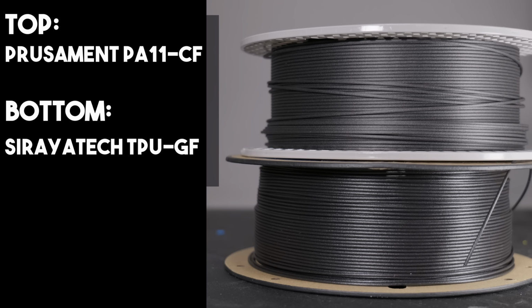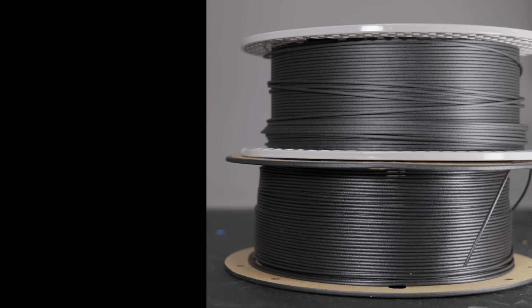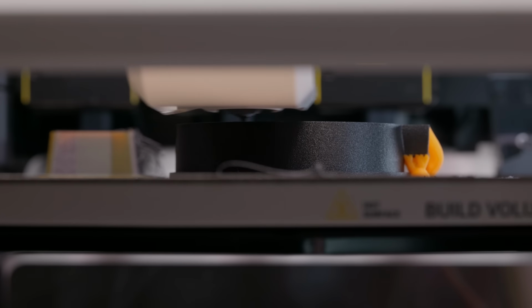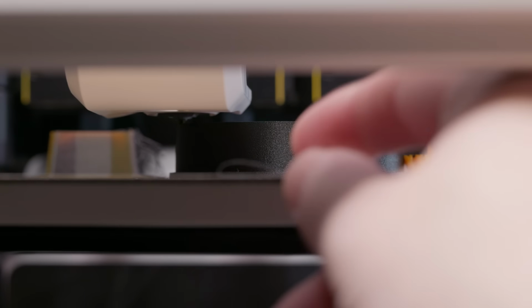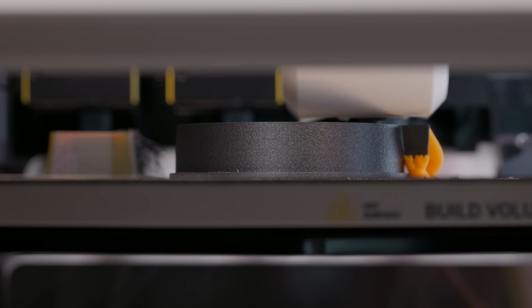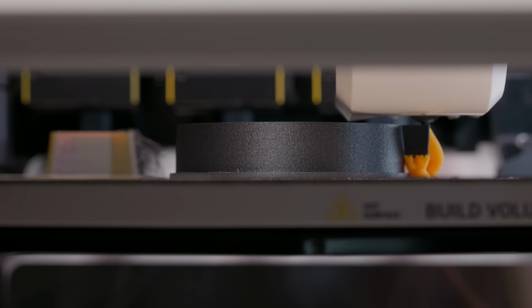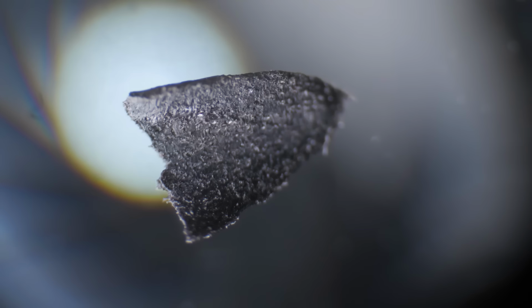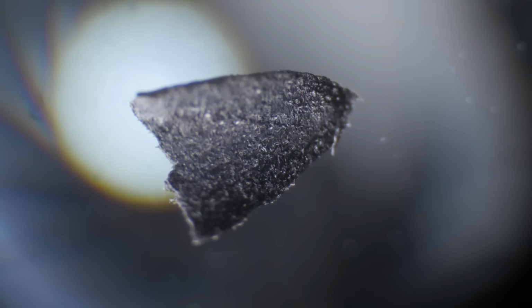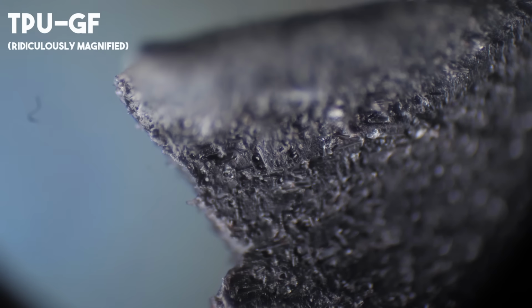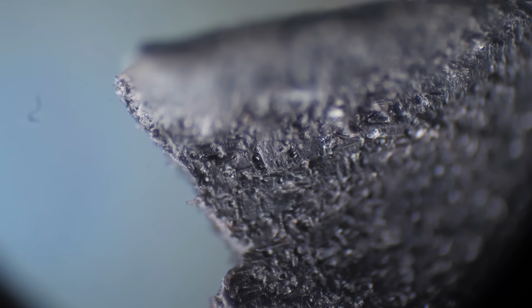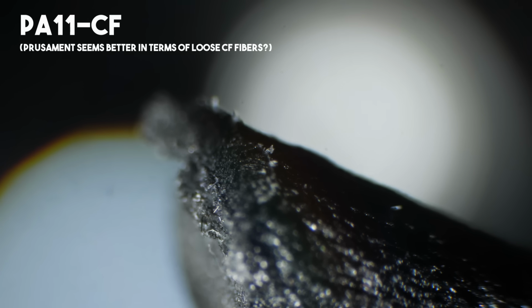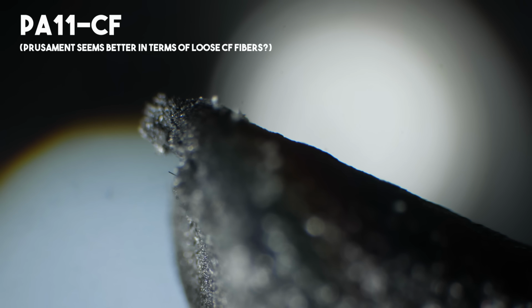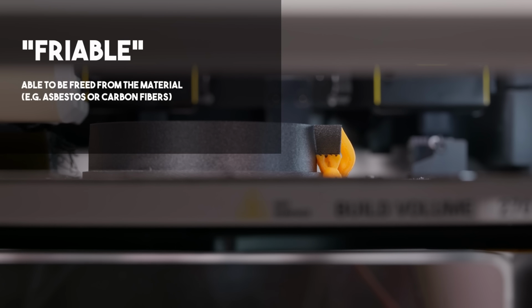The other interesting thing about GF filaments in general, and I've always avoided GF filaments, which is my mistake until recently, because, well, if you've ever had a glass splinter, which you probably have, you'll know that fiberglass itself can be way more annoying than carbon fiber filament, but actually, weirdly, that's not the case for filament, or at least especially TPU GF. In fact, no matter how much you bend or break the filament, you really don't get the same splinters that you will see in CF filament under a microscope. It's funny because this makes glass fibers a relatively good match for 67D TPUs like this. They're both flexible. As a result, we avoid what we call friable fibers.